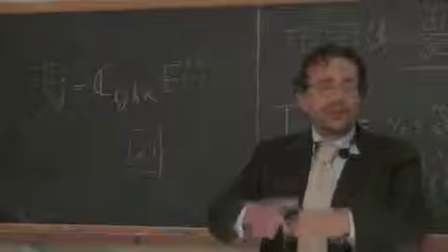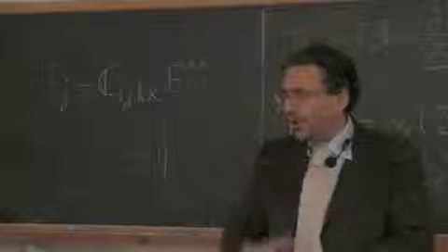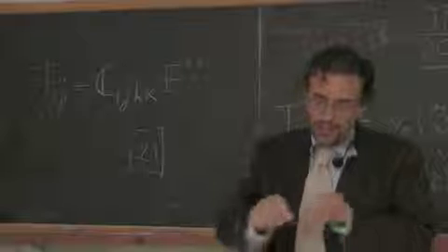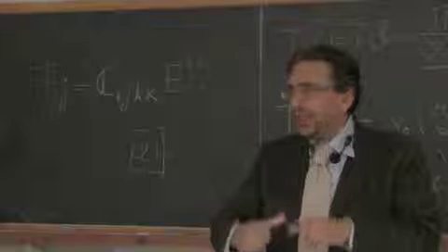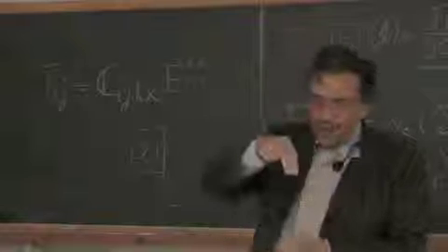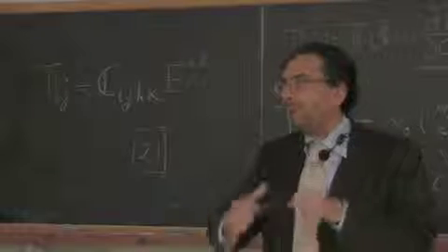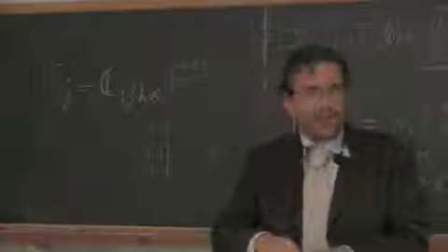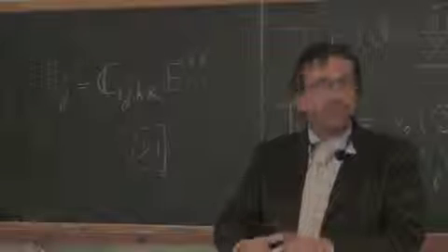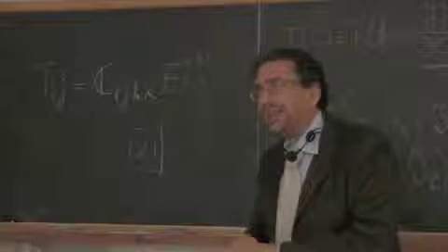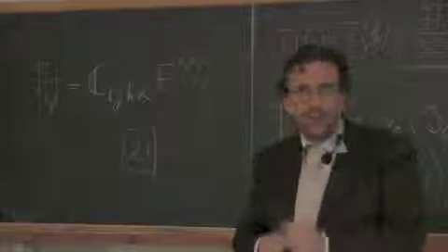Then you consider a much more rigid lateral wall. I mean, you need to embed this cylinder in a hole built in a material much more rigid than the material you are studying, so that the lateral wall will not move, so you have a constrained measure, and you do the same stress-strain measurement. In this way you measure the two coefficients of an isotropic material.